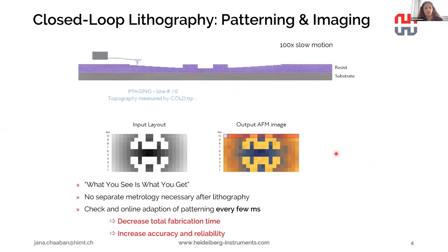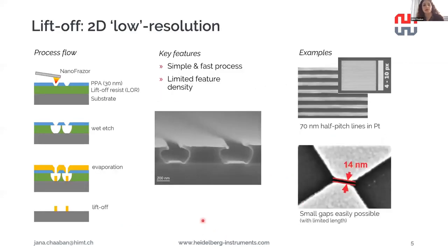But in the end, we don't just want to pattern shallow features in resist. We also want to transfer these high resolution features to functional materials in order to fabricate nano devices. So I'll go over the different pattern transfer techniques that we can use in combination with this patterning method. The simplest one is using a bilayer liftoff, which I'm sure many of you are familiar with. In this case, we just spin coat our thermally responsive resist on top of another liftoff resist. We go on with the patterning as usual on this PPA thermally responsive resist. Then in the next step, we do a wet etch process to create this undercut here.